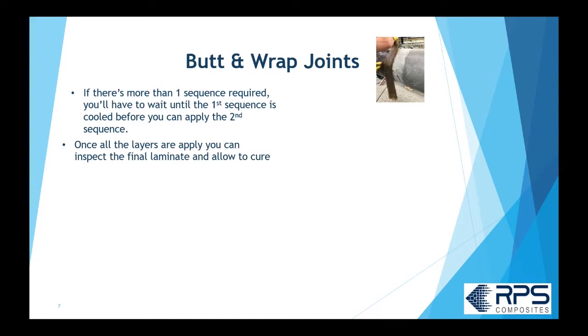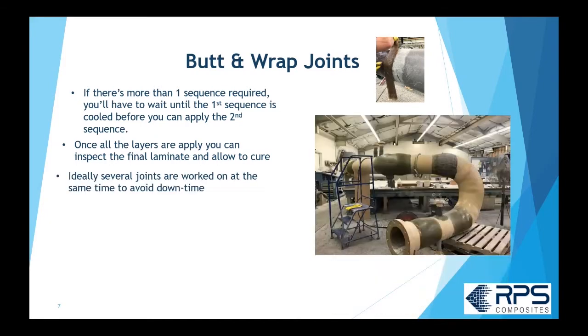And once all the layers are on, you can do a final inspection. Of course, you're doing that while you're doing the laminating, but once all the layers are on and it's cured, you do a final inspection, make sure it's within the allowable amount of defects. Normally, as I'm saying, you're allowing one to cool down. On a spool like this, for example, you may have several joints going on at the same time, so you're avoiding downtime and you're being efficient.